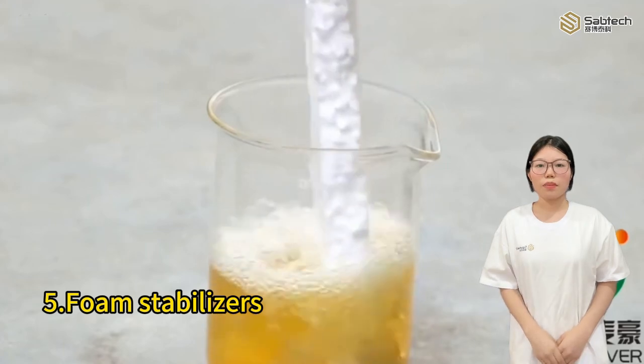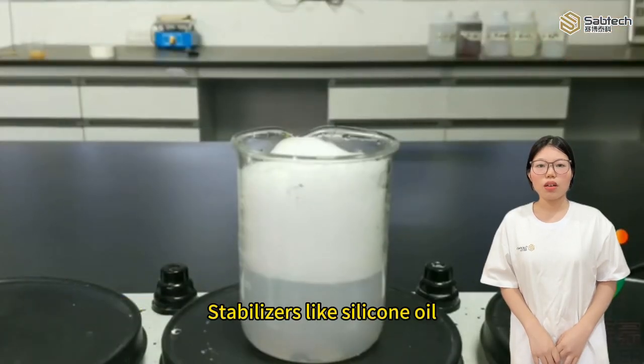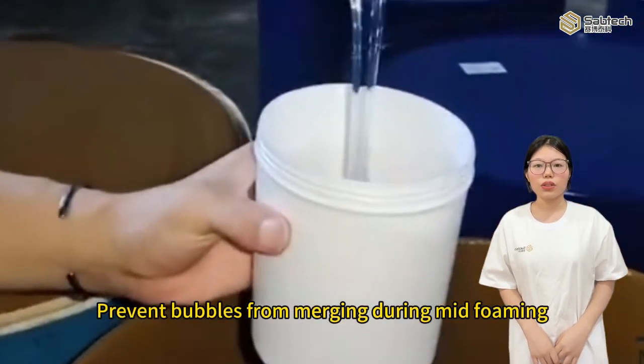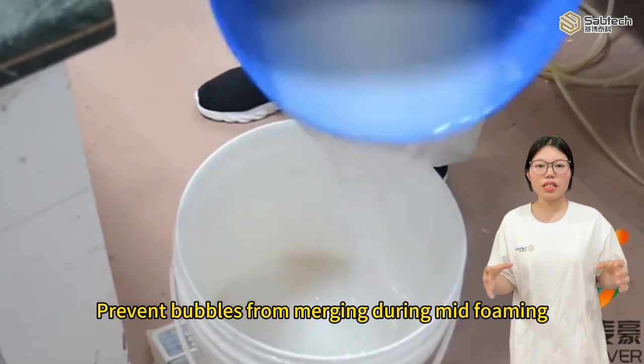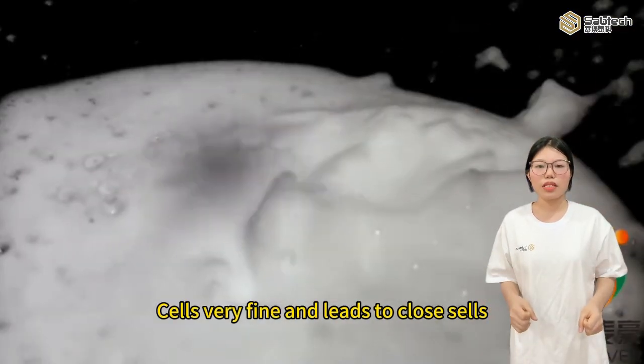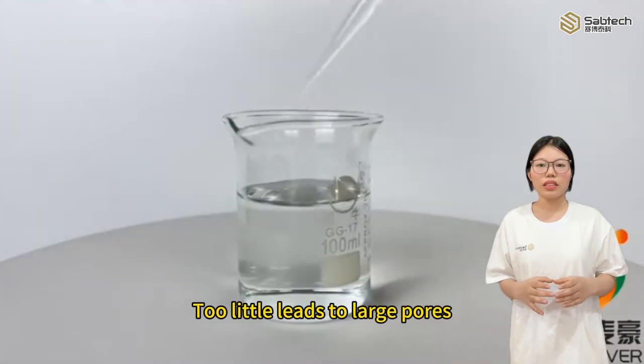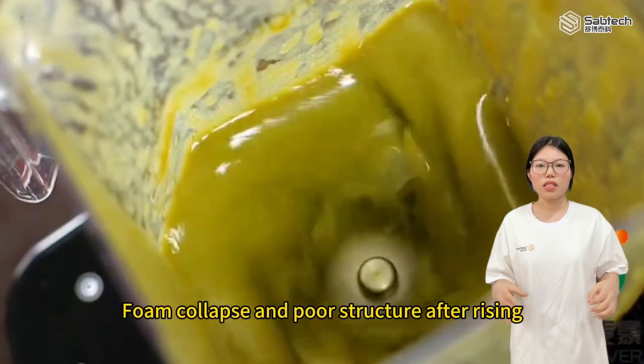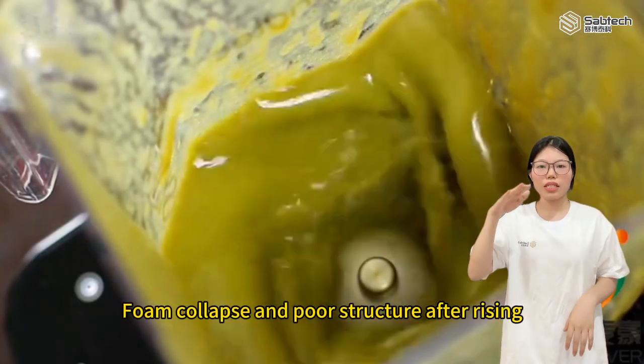Fifth, foam stabilizers. Stabilizers like silicone oils prevent bubbles from merging during mid-foaming. Too much makes the cells very fine and leads to closed cells. Too little leads to large pores, foam collapse, and poor structure after rising.